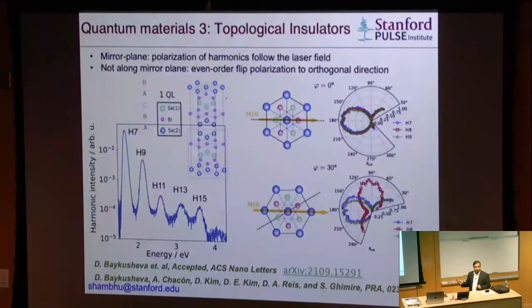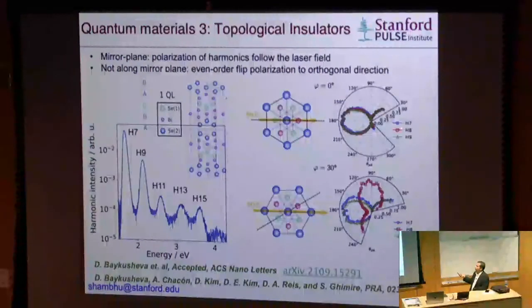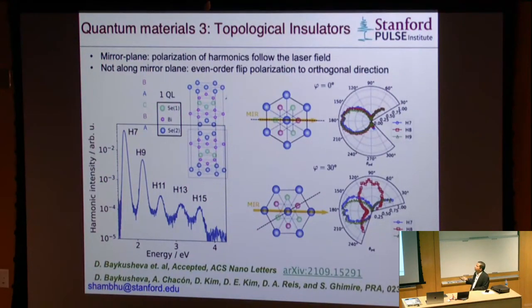Again, very simple experiment. We rotate the crystal with linearly polarized light, and sure enough, we see all harmonics are polarized in the same direction. And the crystal structure is also such that if you are looking from the top, the first layer has some planes that do not have inversion symmetry, as shown there. This dotted line is the mirror plane.